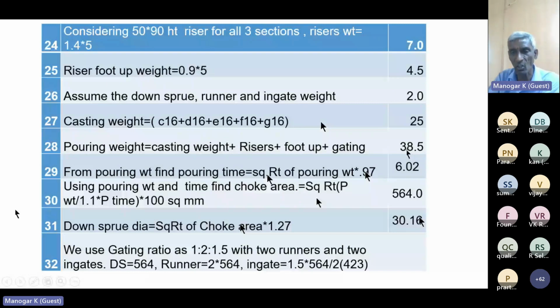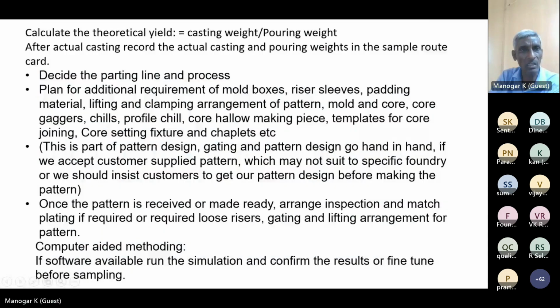That is the choke, that is the down sprue diameter, because in steel casting, the down sprue area should be 30 mm dia. Then using the ratio 1:2:1.5, calculate the runner size, and the runner area and in-gate area are given here. Calculate the theoretical yield, casting weight divided by pouring weight. After actual casting, record the actual casting and pouring weight in the sample route card.